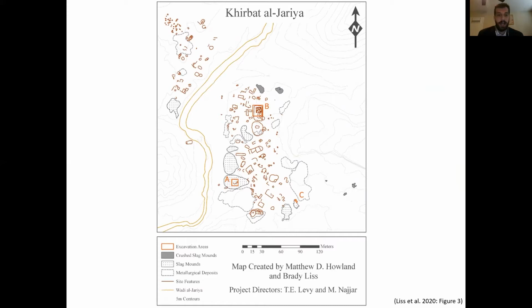You can see area A in the kind of southwest portion of the site on top of the slag mound. That is the 2006 excavations. And then in 2014, 2 new excavation areas were opened. Area B, which was a stone structure kind of in the center of the site. You can see it kind of dead center of the map here. And then area C, which was a slag mound probe on the southeastern edge of the site.